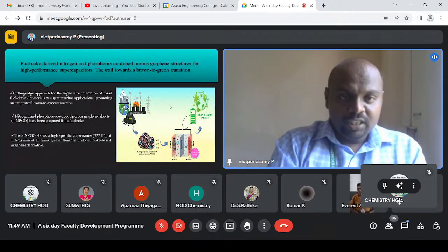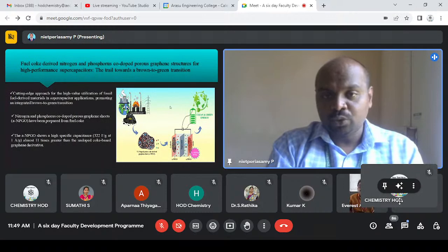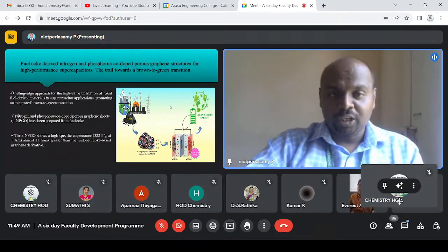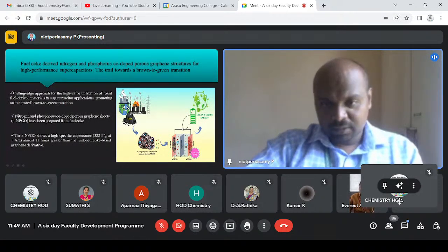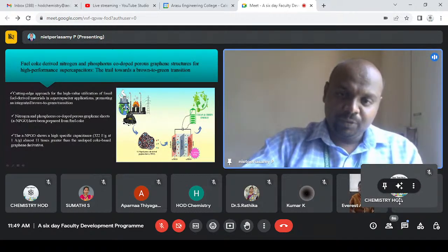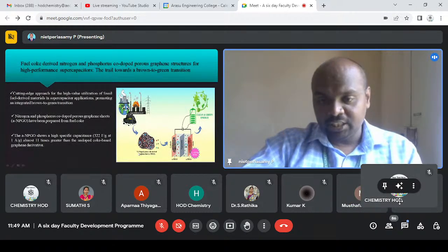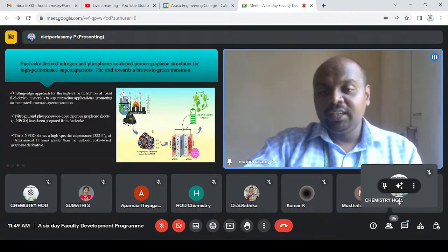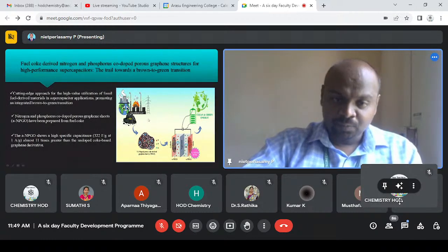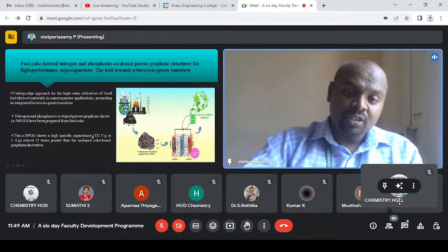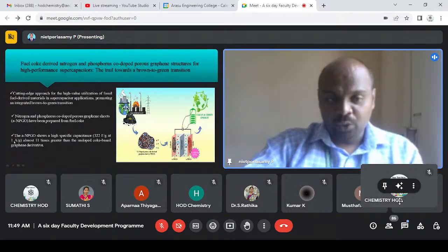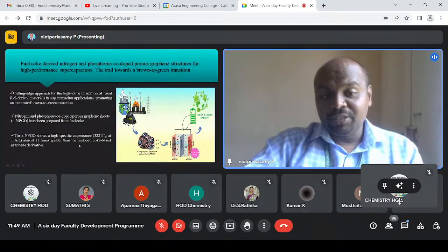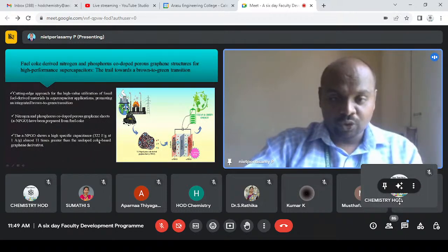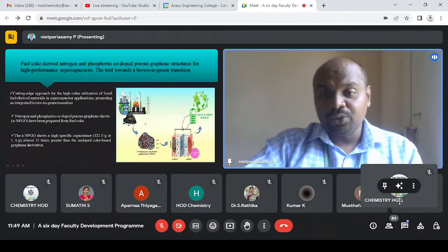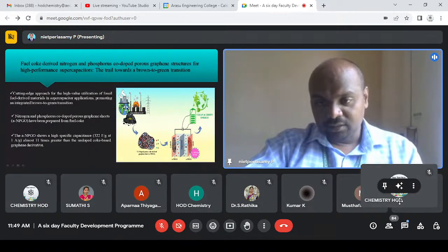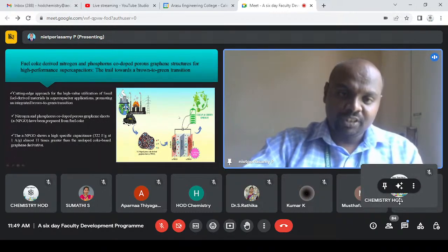My second report is on fuel coke derived nitrogen and phosphorus doped porous graphene structures for high performance supercapacitors. Here they prepared the graphene material from coke and doped it with nitrogen and phosphorus, so that its chemical and mechanical properties are enhanced. They achieved a high specific capacitance of 322 F/g at 1 A/g, almost 11 times greater than the undoped coke-based graphene derivatives. Coke here means carbon-based graphene derivatives. This is also a remarkable report. They also prepared a flexible supercapacitor device.